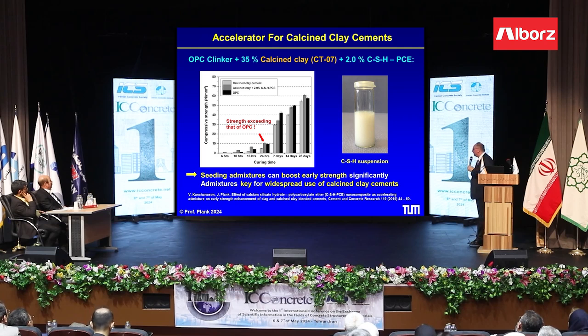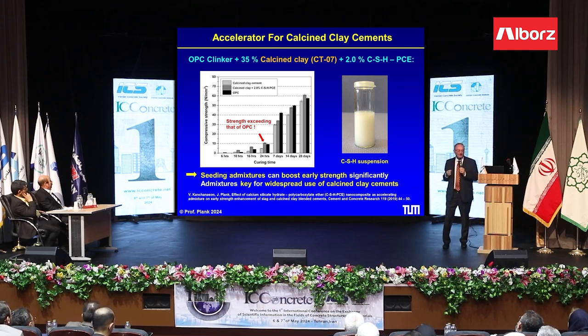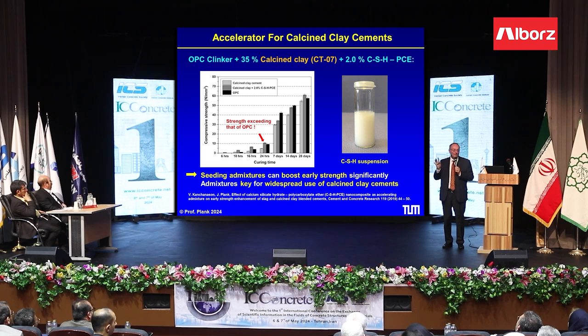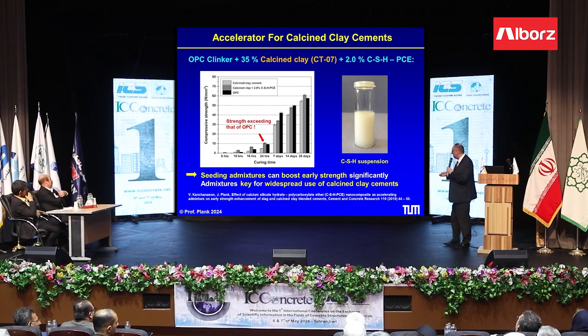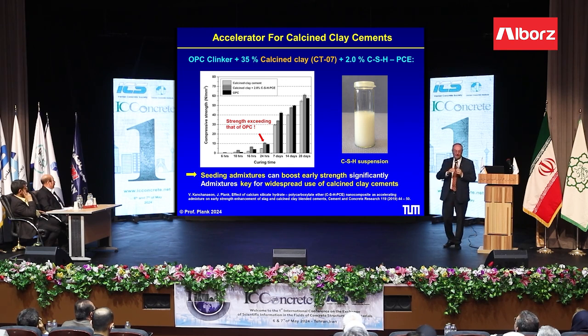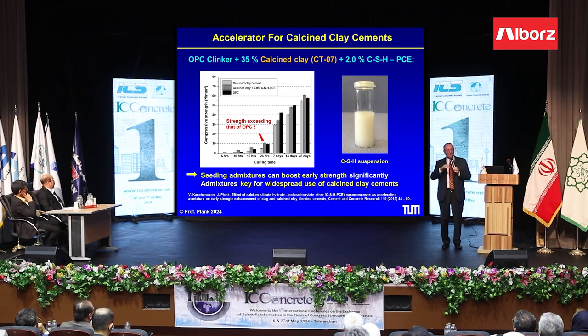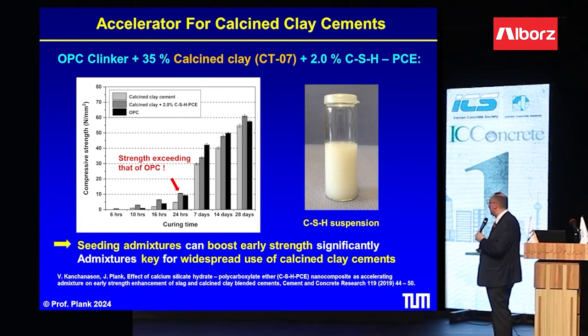Now, what we recommend, if somebody wants to use a calcined clay, is to use a raw clay which has not a high kaolin content, but a relatively moderate one, like 10 to 20%. And here we tested such a German clay, which we calcined, and the PCE dosage demand is much better and slump retention is much easier to achieve, but this cement has a slower reactivity. So we need an accelerator to get high early strength in Germany.